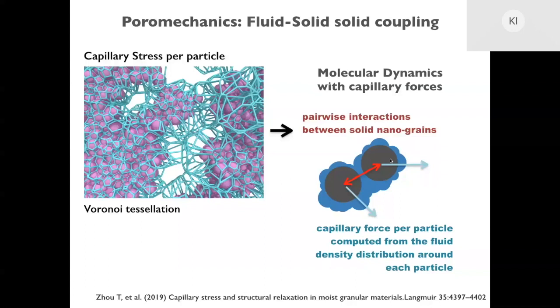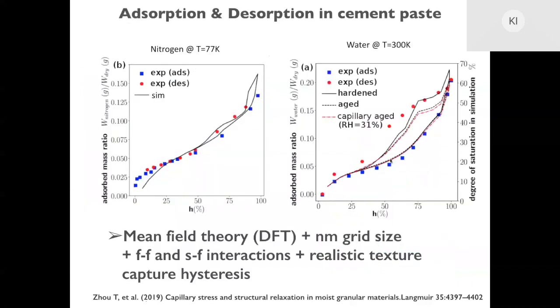at different relative humidities. So now that I finished with explaining you the technique, we'll go through the results of this study. So the first interesting result is the adsorption and desorption of nitrogen and water in cement. So this again is something that a lot of people have been trying to model to obtain the hysteresis, especially in the case of water, but I think nobody could have an agreement up to now. So as you see here on the figures, we have a very good agreement with experiments. Of course, in the case of nitrogen, the hysteresis is very small, but in the case of water, we're able to capture all these ink bottle effects that are giving rise to the hysteresis.